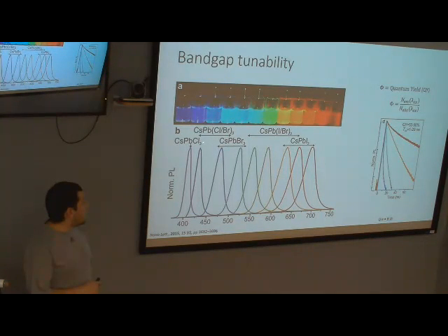As you can see, using a smaller halide such as chlorine, compared to iodide, we got more of the UV range of the visible spectrum, while when we used bigger ions such as iodide, we got closer to the IR range. So the band gap tunability is really simple with these structures, because just depending on the composition of your perovskite, you're able to have varying amounts of color.